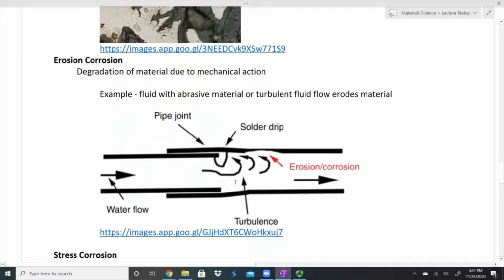We have erosion corrosion, degradation of a material due to a mechanical action. There's a picture here. I looked up some pictures online. They all looked somewhat similar, and so it wasn't helping kind of get a picture of what's happening. So I found this little cartoon instead. If I put two pipes together and there's going to be this solder drip, this little solder point here, I have water flow. This little drip here, this little inconsistency in where my pipes join together is going to cause some turbulence. This turbulence is going to speed up this water and it's going to erode away part of my pipe at a faster rate because of that speed, especially if there's something inside of this water.